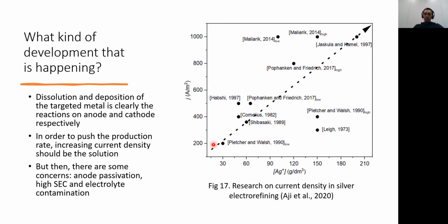The correlation is that for higher current density processes, it seems from these publications that they have higher silver concentrations in the solution. This is what intrigued me to study high current density silver electrorefining further. To put these figures into perspective, I put these three bullet points. Dissolution and deposition of the targeted metal is clearly the reaction at the anode and cathode. To push the production rate means pushing dissolution and deposition higher, so of course increasing current density should be the solution.